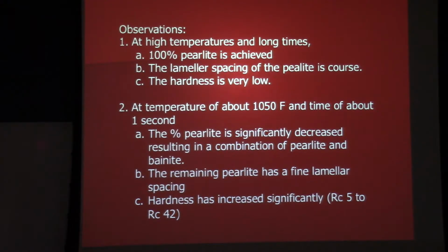So some observations at this point. At high temperatures and long times, we would get 100% pearlite. The lamellar spacing of the pearlite is very coarse. We were talking about that already. And the hardness is very low.